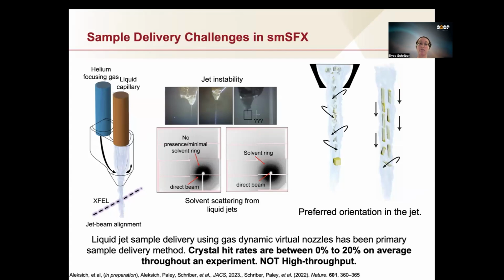For material science, it's not as challenging as we tend to have higher scattering factors. One of the difficulties of liquid jets is that we run into a significant problem with jet instability. The XFEL beam, which is about 1 to 3 microns in size, has to overlap with the jet, which is usually about 5 to 10 microns.